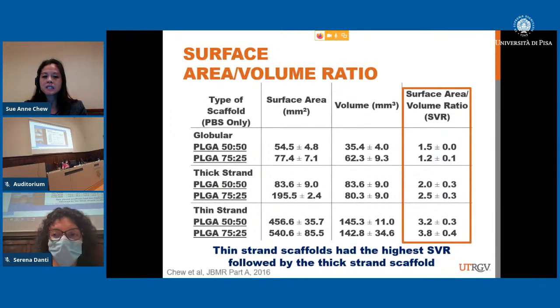Okay, so we made the different architectures: the globular, the thick strand, and the thin strand, right? Globular was with the syringe, the thick strand was with the 1000 microliter pipette, and then the thin strand with the 200 microliter pipette. So we can see here that the surface area and volume ratio could be changed based on that. Something that is thin results in higher SVR, surface to volume ratio, which we believe can lead to faster degradation, right, because of the more surface area, and also a faster release of the drug.